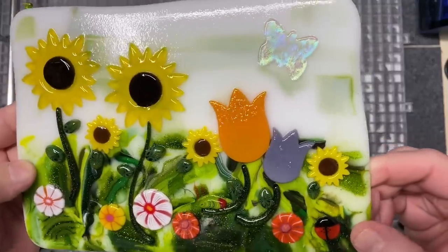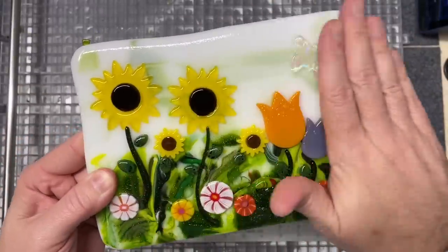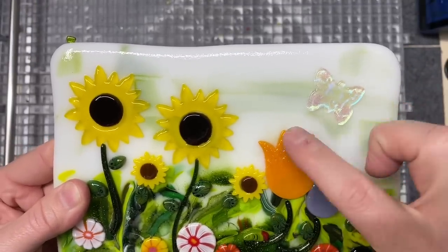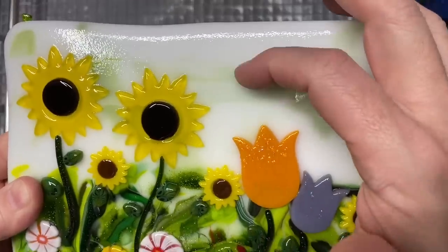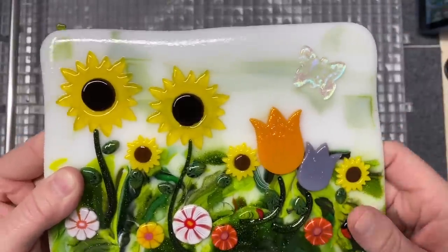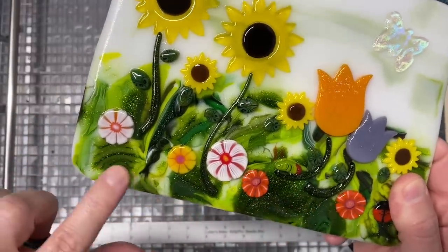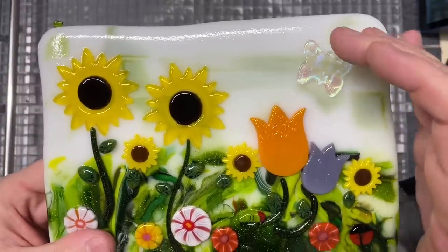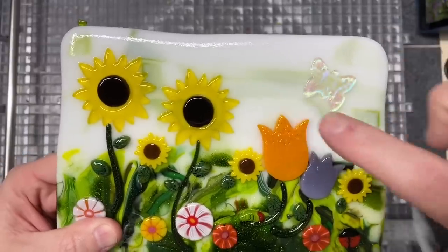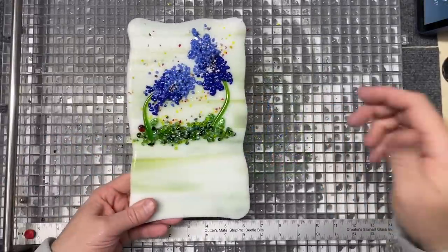What's interesting — I think the video is picking it up — this white is relatively prone to devitrification, so I dusted a pretty good layer of clear powder over the whole thing. On the other pieces the clear powder fused right in, but on the white it almost made this texture. You can definitely hear that — glass doesn't usually sound that way. It's not as textured on the bottom, really just on the white. I think the white was devitrifying and then grabbed the clear — I don't know the exact mechanics, but I don't dislike it. I'm not sure I could replicate it if I tried.